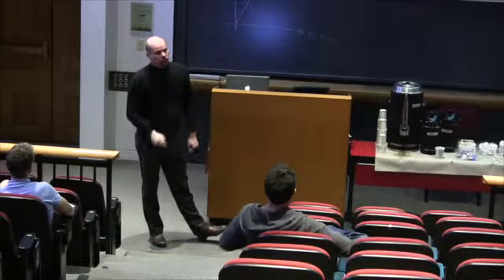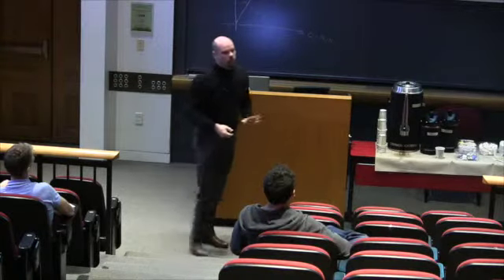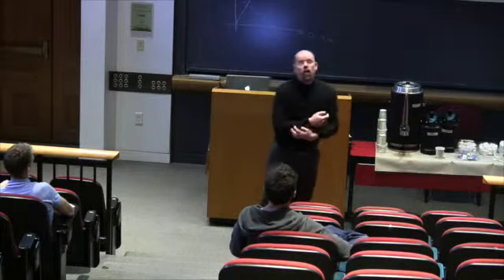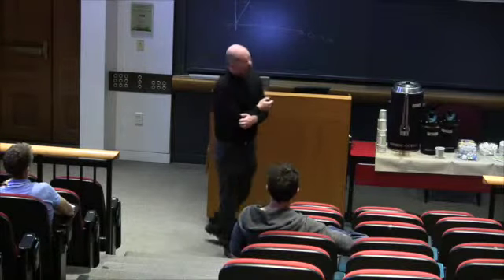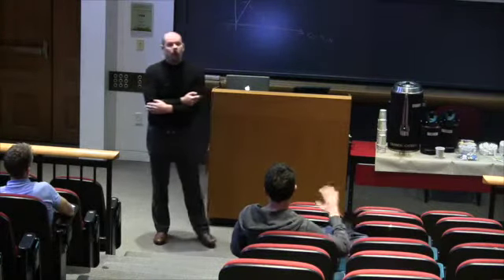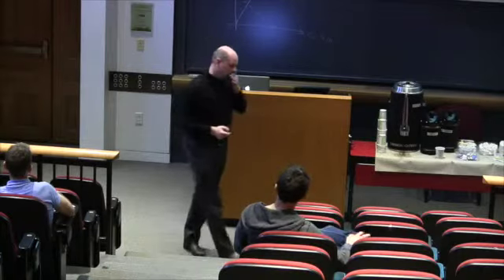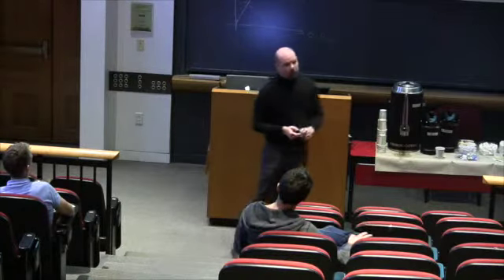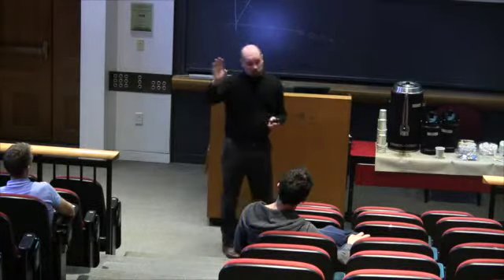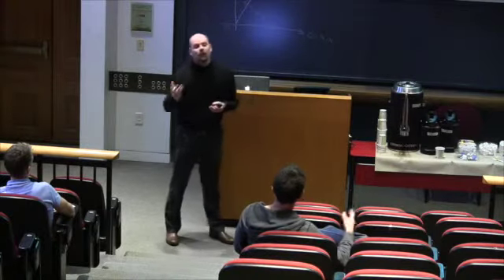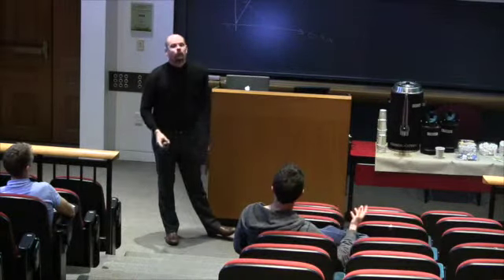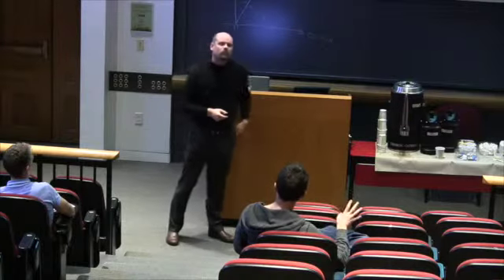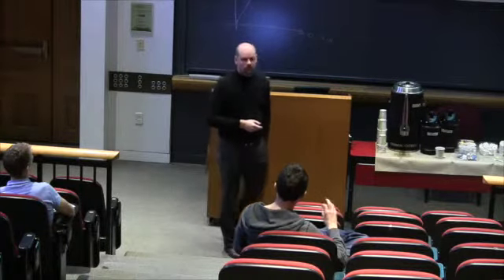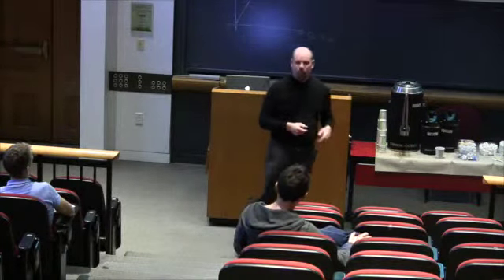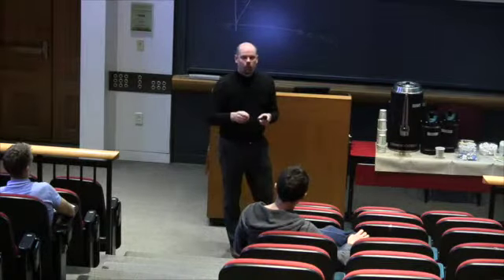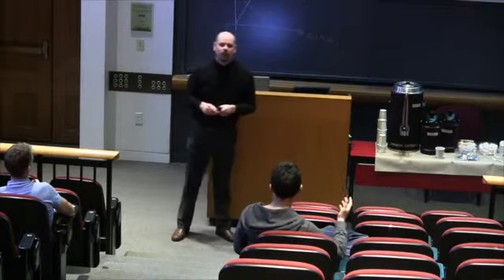But this doesn't give you the intensity. It's checking consistency, because it is for magnetic or non-magnetic. And of course you do have form factors. Right? So yes, neutron scattering, they typically calibrate on phonons. They say they know the cross-section on phonons very well. That gives them the intensity for this spin flip. Can you calibrate on something else? No.